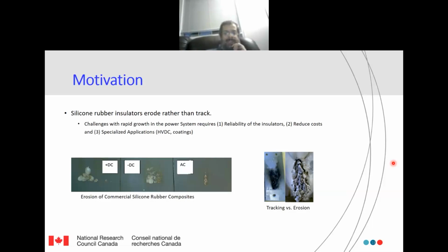This is something Dr. Muhammad will come back to later on, and this is very, very important: once you start to have arcing on the surface, two phenomena will take place, tracking and erosion. Tracking is when you have a carbonized path on the surface, which will enhance the development of the leakage current even more. Why? Because carbon is a conductive material. So this is extremely bad.